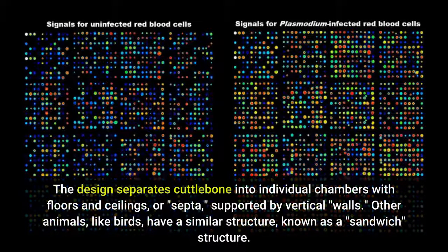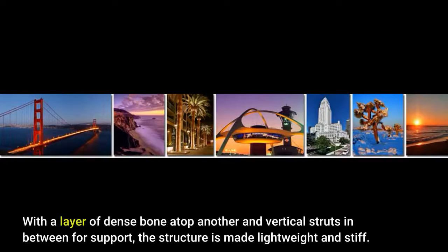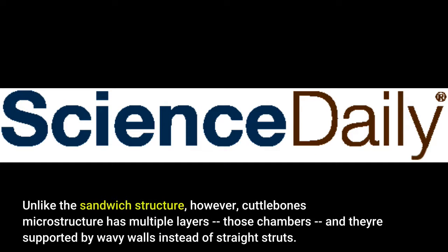The design separates Cuttlebone into individual chambers with floors and ceilings, or septa, supported by vertical walls. Other animals, like birds, have a similar structure, known as a sandwich structure. With a layer of dense bone atop another and vertical struts in between for support, the structure is made lightweight and stiff. Unlike the sandwich structure, however, Cuttlebone's microstructure has multiple layers, those chambers, and they're supported by wavy walls instead of straight struts. The waviness increases along each wall from floor to ceiling in a waviness gradient. "The exact morphology we haven't seen, at least in other models," said Li of the design.